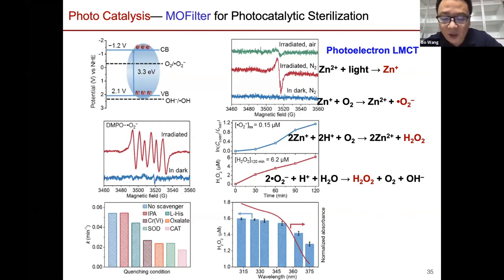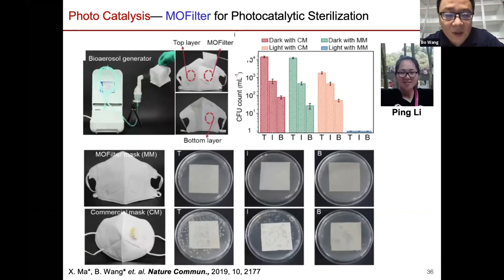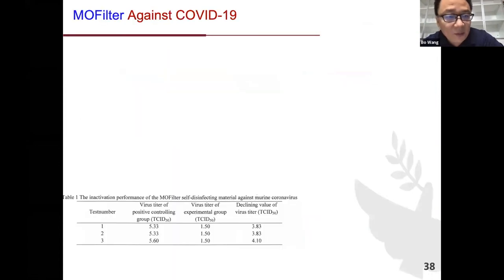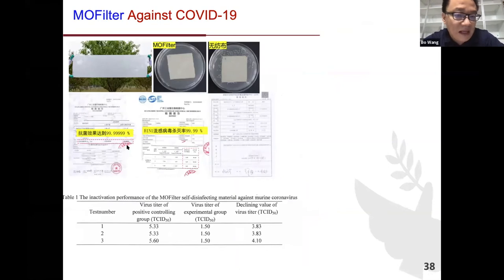So using that hydrogen peroxide, we can effectively kill the bacteria, in this case E. coli. And it will give you a very nice mask. Not only can it filter out some of the aerosol we're facing, at the same time it can kill the bacteria. Using that, we did a little bit of work against coronavirus. Since we can mass produce such small filters, we tested for different types of bacteria, viruses like H1N1, and then we also tested for coronavirus.